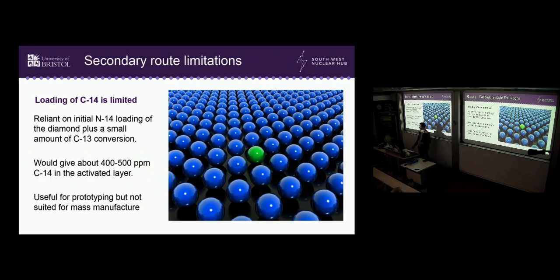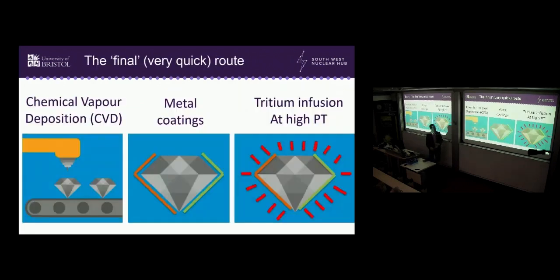So it's really useful for prototyping, but it would never be the type of diamond battery which gives us our highest power output. The highest power outputs will always come from the high purity carbon-14 tritium type devices, which I've already told you about. And in the last year, we've developed a third route as well, which is you grow your entire device minus any carbon-14, but you grow a Schottky diamond device, all finished with its metal electrodes and everything, and you stick it into a system, the kind of system that you have, Tim, where you expose it to hydrogen at a relatively high pressure and temperature, and you infuse the diamond with deuterium, if you want to stick in a reactor for activation, or you infuse it with tritium, which is the quickest way.